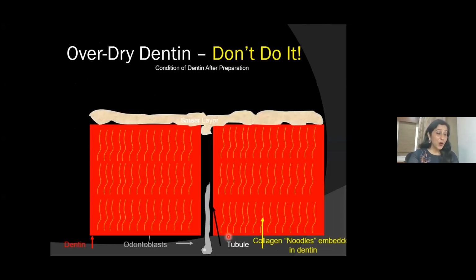So let's see what happens when you are using total etch technique. Then the dentine etching needs to be done in the right fashion. When we are talking about the total etch technique, you etch enamel and you etch dentine. In selective etch, you etch only enamel, but you don't etch dentine, and you use self-etching adhesives so that they can bond to enamel and they can etch and bond to dentine as well.